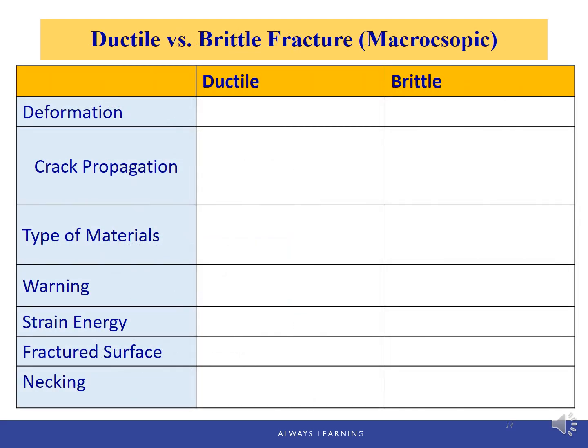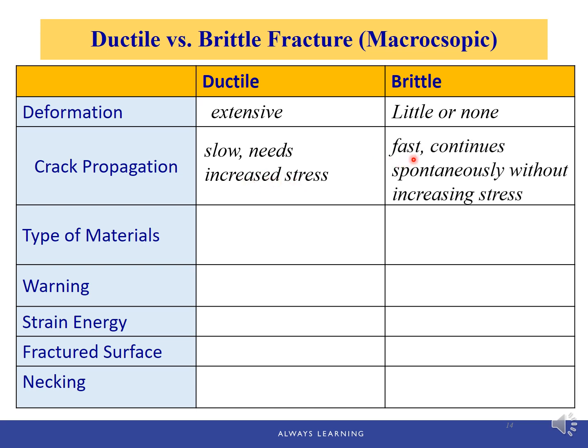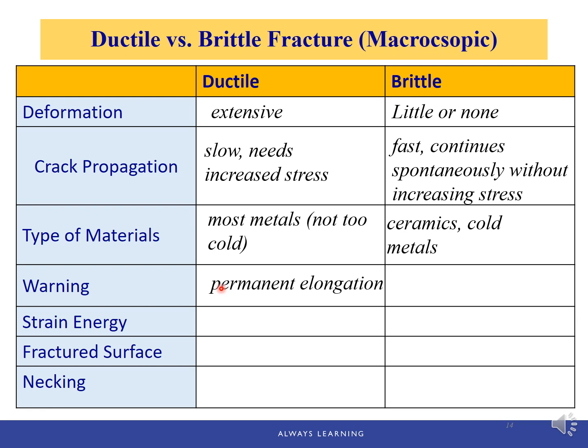Now we can compare the ductile and brittle fractures from a macroscopic perspective. First, the deformation. Ductile fracture has extensive plastic deformation, whereas brittle fracture has little or none. And for ductile, the crack propagation is slow and it needs increased stress for the crack to grow. For brittle, the crack propagation is fast. It continues spontaneously without increasing stress. And type of materials, most metals will have ductile fracture at a temperature that is not too cold. For brittle, it usually happens in ceramics or cold metals. And ductile fracture has some warning because of the permanent elongation or extensive plastic deformation. It gives warning. But for brittle fracture, there is no warning before the fracture happens.